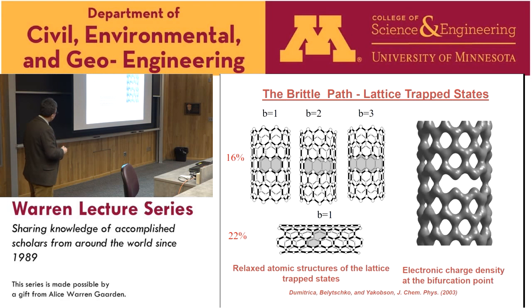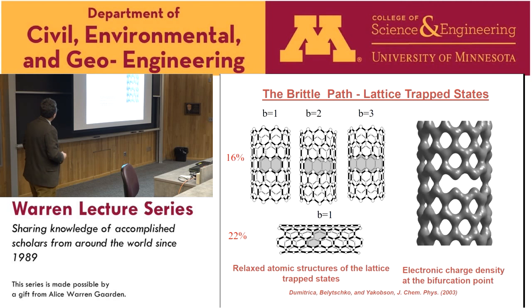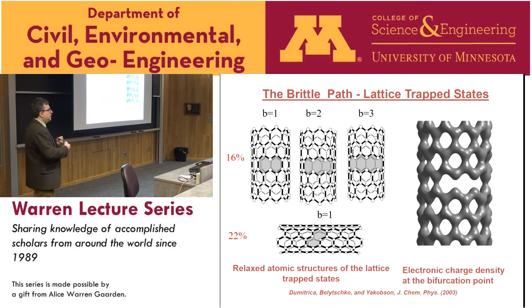Here we study with quantum methods how fracture develops in carbon nanotubes. These are zigzag tubes where you have bonds along the axial direction. Around 16% stretching, we find that bonds are breaking. We identify a set of bond-breaking crack states B1, B2, B3, with two, three broken bonds, at which the electronic charge is missing. What you see here is the electronic charge cloud — it's very strong when you have large stretching.